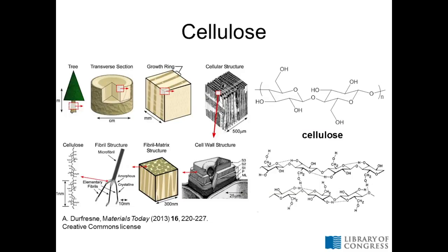If anyone remembers the really fantastic Powers of 10 video that zooms in and out at different length scales, you can see what materials are at what scales. Cellulose really is the fundamental building block — about as small as you can get when you start from the raw material, from trees or wood-based or rag-based materials, all the way down past the cellular structure, past cell walls, past fibrils, past fibers, down to cellulose. What cellulose looks like is a string of sugar molecules linked together — that's what the N represents — over and over to make a very long chain polymer. There's even more complicated structure with hydrogen bonding both within and between cellulose chains, but it really is the fundamental material building block that makes up paper.